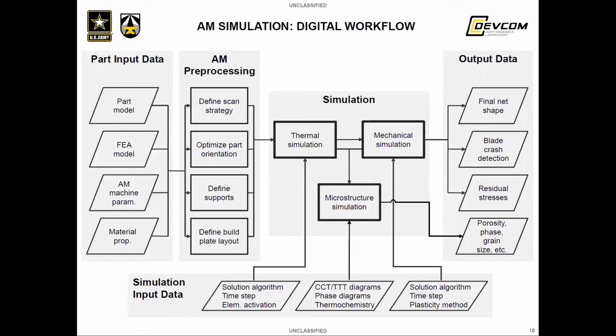The third simulation type listed here is the simulation of microstructure as a function of the thermal processing. And sometimes that'll also include aspects of the mechanical solution when stress is a driver for microstructural change. Here, the thermal history of a single material point can be used in conjunction with various other algorithms to simulate aspects of microstructure. Microstructural quantities of particular interest for AF9628 include porosity, phase content, prior austenite grain size, and others.